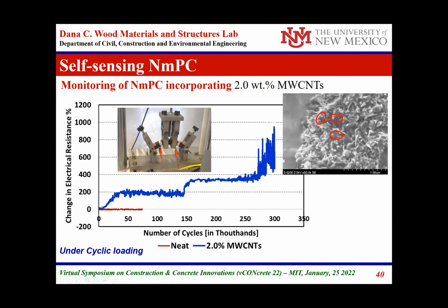While the nano-modified polymer concrete, you can see here the significant improvement in its conductivity, or change in conductivity, and a significant improvement in the material, which doesn't fail under a large number of cycles, up to 300,000 cycles of load. And interestingly, this electrical change matches very closely with the typical mechanical damage change we know, where it goes through the typical cycles for fatigue: primary, secondary, and then tertiary, up to failure.